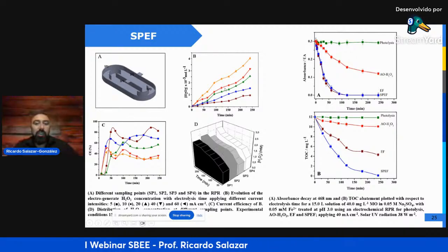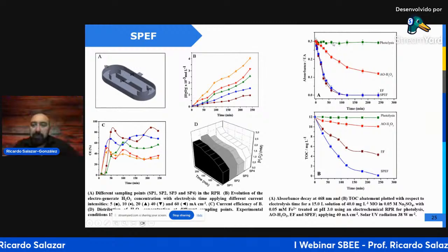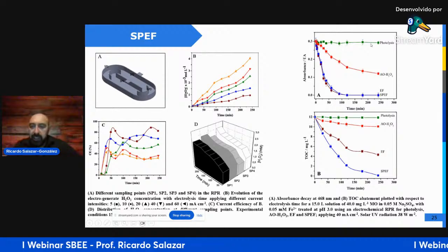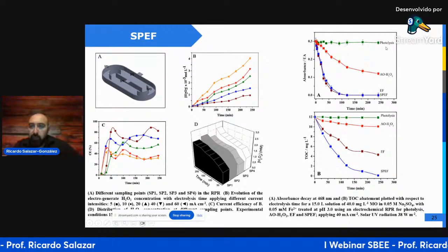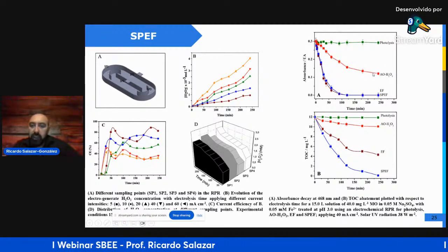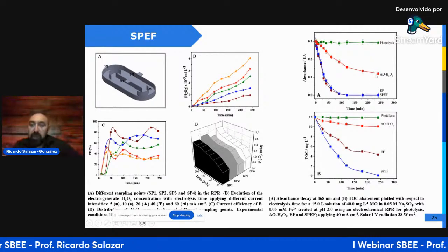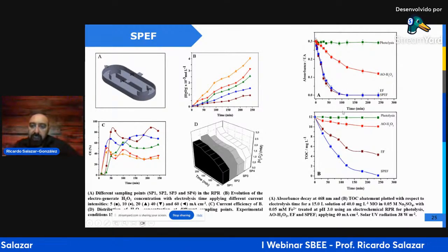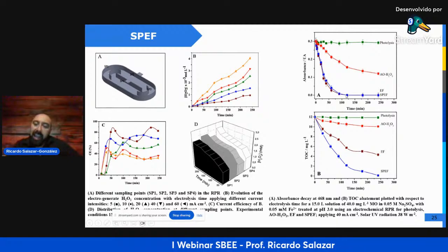So with this result, we applied the solar photoelectro-Fenton process and studied that the concentration of the pollutants is maintained during 3 hours of the solar photolysis. If we have only the anodic oxidation, the decolorization of the solution is a little more than 50%. And we obtained the complete decolorization when the electro-Fenton and solar photoelectro-Fenton processes were applied.